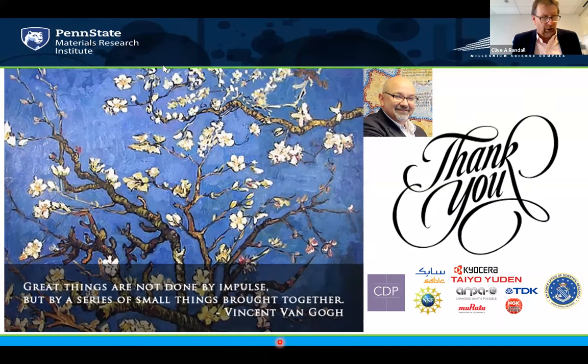And I can't give you a number at the moment, but for example, I showed my student's work on the beta alumina. He was whacking this thing with a hammer to try and break it and actually create a fracture micrograph, a microstructure, for some of those images. So I think there's a lot more to be done in the mechanical space for sure. And I think it's very easy to make a weak cold sintered grain boundary by not understanding the details of the transient phase and the evaporation and the closing of porosity. But if you do understand why all those things are important, as opposed to just doing it, and give yourself time to do it, you could actually push the mechanical strengths up. I do believe they may not be quite as strong as the bulk materials, but I think you can close the gap more than what's been reported so far.